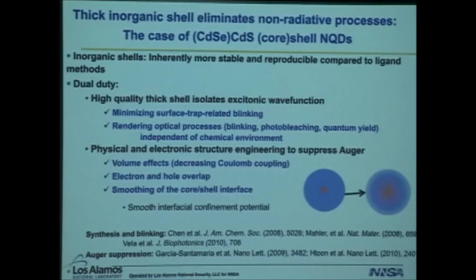And then lastly, theoretically it was shown by Sasha Efros some years ago that potentially if you blurred the interface between the core of the quantum dot and its shell, such as by forming an alloy, for example, by smoothing the interfacial confinement potential, that itself could also additionally impact Auger. And so we sought basically a system that would allow us to achieve this combination of beneficial effects.